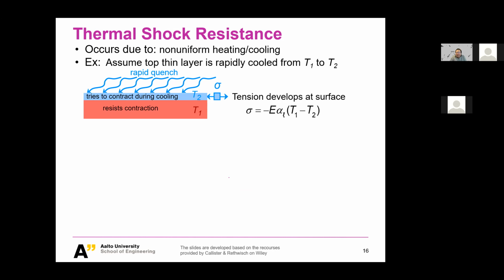This is not specific to, let's say, a wire. It is actually general to any material, because this is related to one heat treatment process, so-called heating and cooling. Especially when we do the quenching process with fast heating or cooling, because that usually induces a non-uniform temperature profile in our material. Maybe remember when we do the quenching, the surface always has a higher temperature decrease than the center. So you probably have a higher temperature in the center and a rather low temperature at the surface.